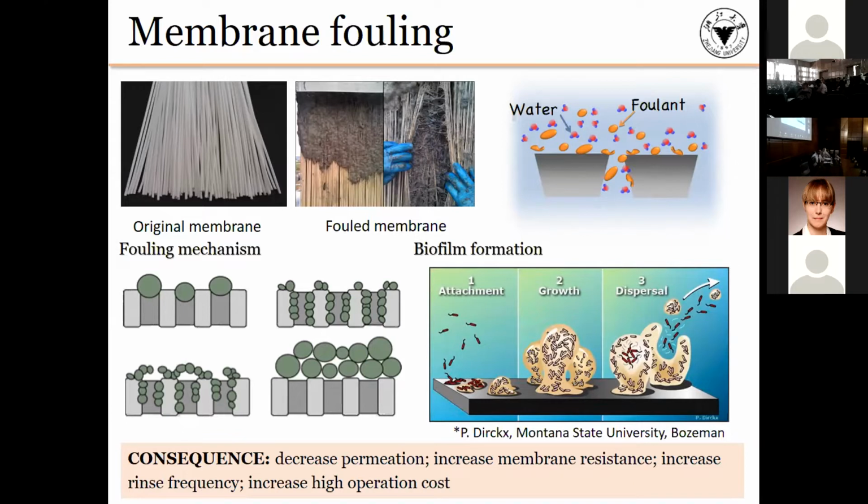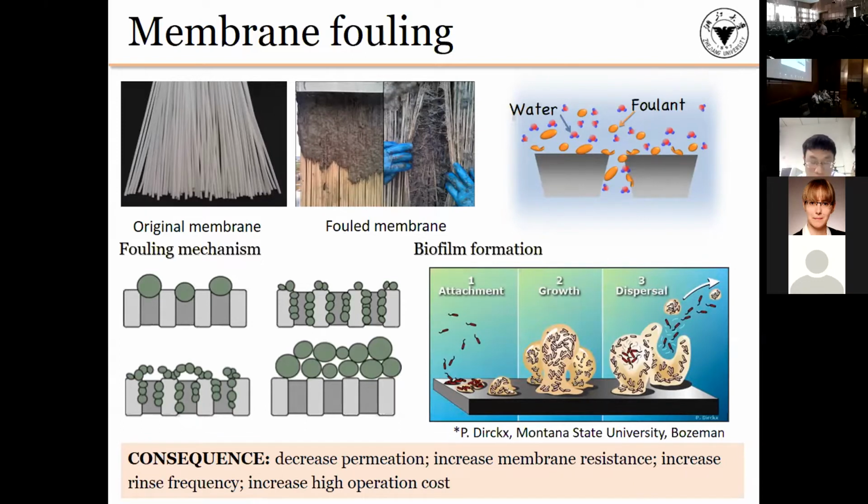Surface property, different from the organic foulant. The bacteria can not only attach on the surface, but also can grow on the surface. Moreover, the dead bacteria, as well as the cell matrix, become another type of organic foulant which covers the surface. That will block the pore size. So it's important to reduce the foulant adsorption and also avoid the bacterial growth to decrease the membrane fouling.